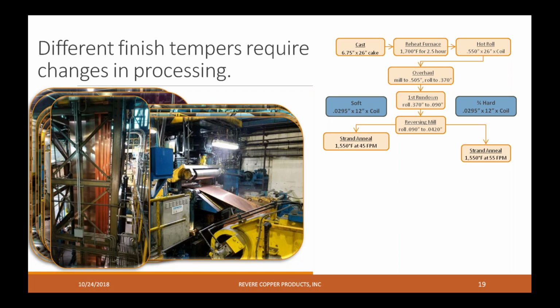But that 0.042 isn't a random gauge. We didn't just roll it from 0.090 to 0.042 because that's as far as we could go. What we're looking for is, in order to get that 3/4 hard on the right-hand side, you have to do a gauge reduction of 29%. So if you want the metal 3/4 hard, you have to reduce it 29%. So to go to 0.0295, the 29% reduction, you have to start at 0.042 after the last anneal. So we get it down to 0.042 and we anneal it. Now on the left-hand side, it's soft. You can see we annealed it slightly slower at 45 feet per minute versus the right at 55. That's because we're looking for soft properties at the end of that example.